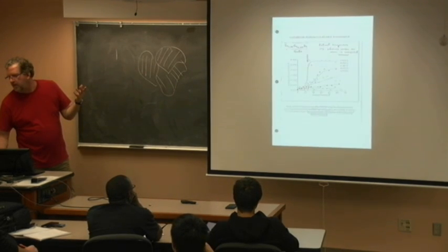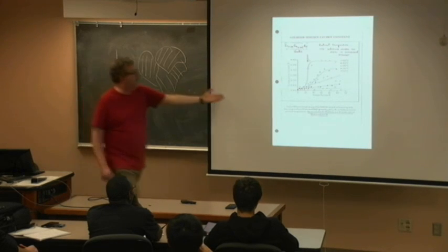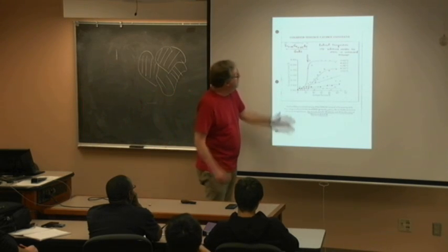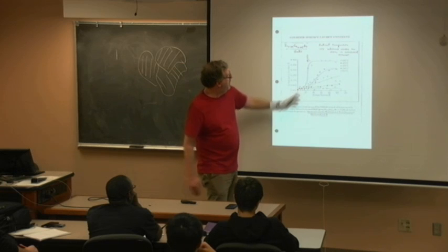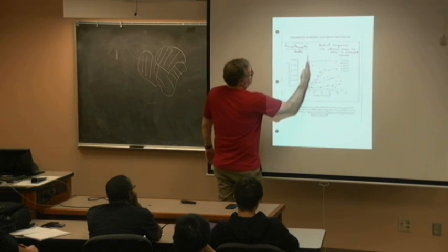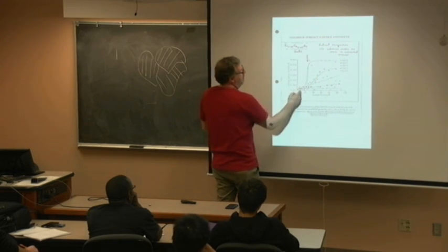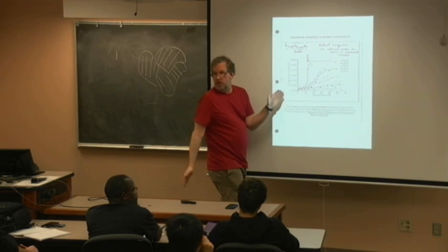Oops, I didn't realize I was going to have to go that far. You end up with this. This is one of my pages out of my PhD. You actually measure that surface lattice constant. So this is the critical thickness. That's from theory. That's what it tells you. And I actually saw that through electron diffraction.